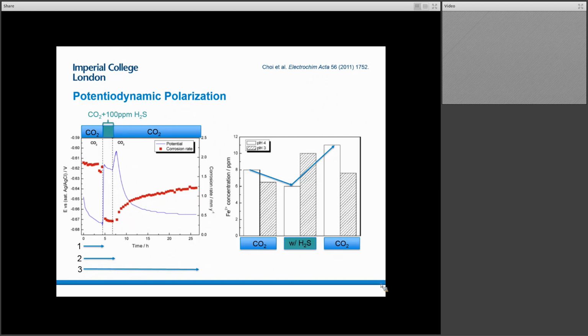And so interestingly, later in the paper, in reference to a slightly different point, but it really illustrates the fact that they observe that the iron ion concentration in the bulk of the solution is changing, again, at the end of these 3 stages. And most notably, they see a decrease in that concentration at the end of stage 2, when they believe that they have that iron sulfide layer formed, i.e. those iron ions have gone somewhere. But by the conclusion of stage 3, where it looks very much like that iron sulfide layer has been removed, all of a sudden you also are seeing an increase in the iron ion concentration in the bulk. So this is starting to, in fact, also close the mass balance, right?